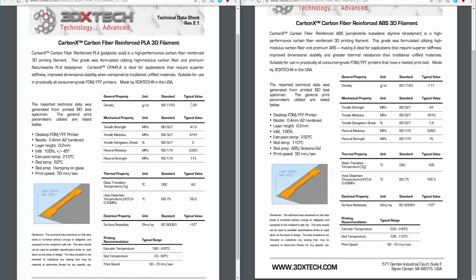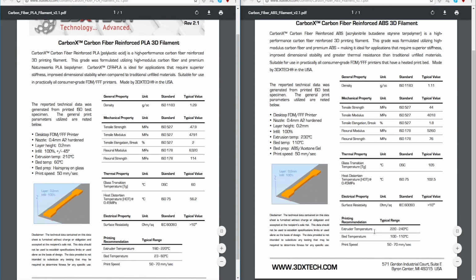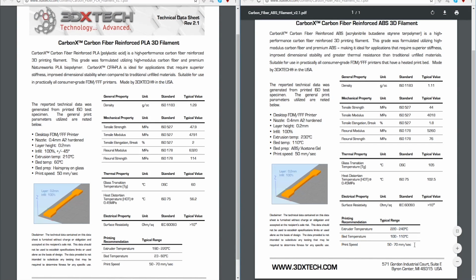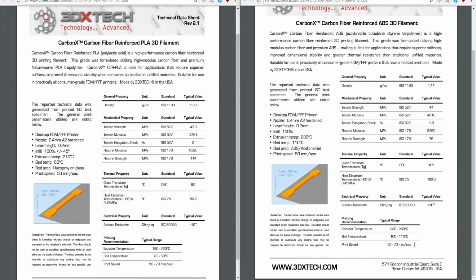So also you notice that this is quite a bit less dense. This is almost 0.2 grams per cubic centimeter lower than the PLA. So it's lighter and it has better temperature stability. But it's harder to print because, as you know, ABS flexes like crazy. So I don't know if I would use this still even without a heated chamber unless you're building really small parts. The smaller the part, the better the ABS is going to print.